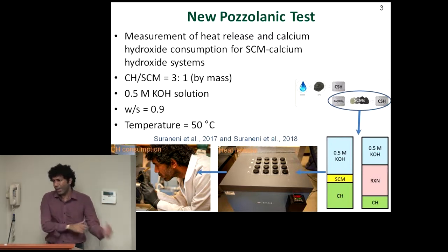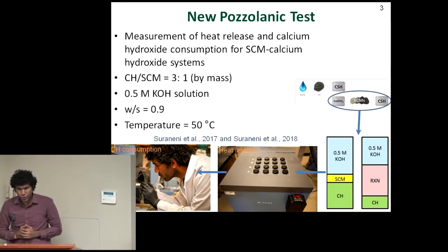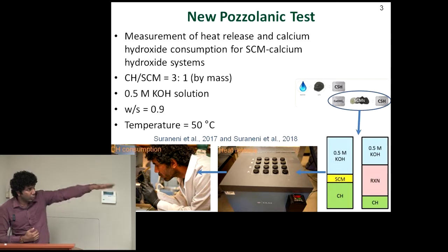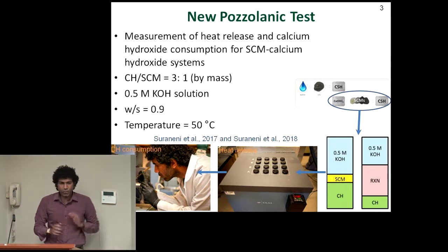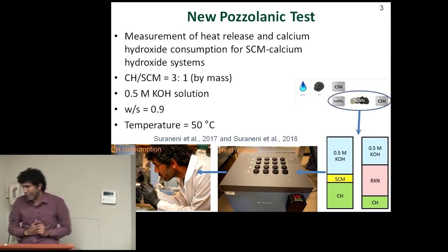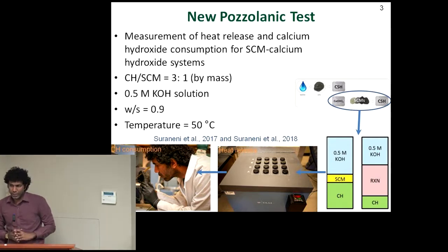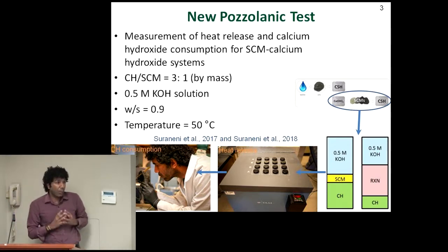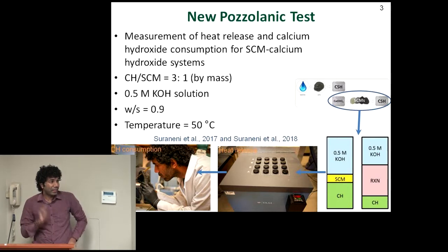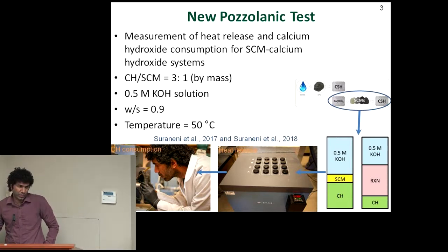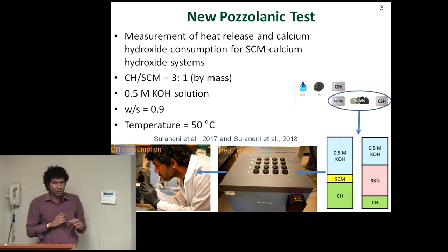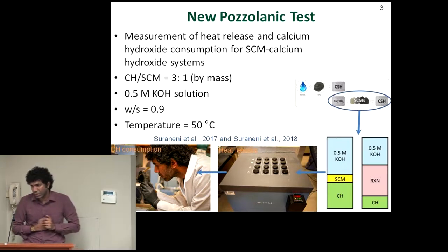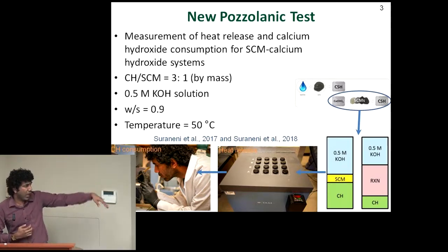So what we do is we have a model system of supplementary cementitious materials and calcium hydroxide, crudely illustrated there. There's a couple of other variables, and I won't get into the details of that. Essentially, we measure two things. The first is how much calcium hydroxide is consumed, and the second is how much heat is released. These are actually not identical, for somewhat complicated reasons, and those are the test methods that you use to do that.